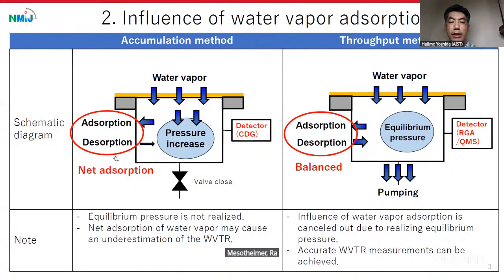In the accumulation method, however, the water vapor pressure keeps increasing. Therefore, the adsorption rate onto the vacuum chamber is always higher than the desorption rate from the vacuum chamber. Therefore, the net adsorption of water vapor may cause the underestimation of the WVTR. Please go to the next slide.